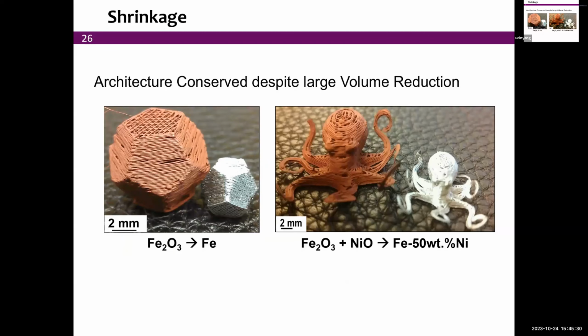And so here are examples. You see the dramatic shrinkage as you go from iron oxide to iron, or this mixed kind of, well, this is actually an Invar type of alloy. And you go from oxide, red, to the metallic shiny material. But what's really remarkable, at least for us, when we did this, is that there's absolutely no distortion in the material. It shrinks in an extremely uniform manner.